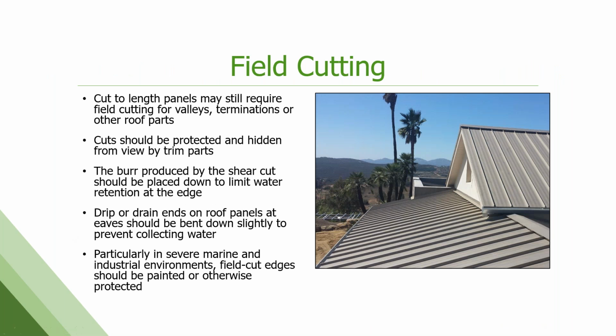Field cutting. Yes, field cuts happen. They need to happen. Valleys, terminations, etc. They should be protected and hidden with trim as much as possible, if that's possible. The burr made during the shearing and cutting action should be down, which allows water to drip off that edge and not hold onto it. And then you can even slightly bend or downturn cut ends or eaves as well to prevent water pooling and capillary action holding on that cut edge. In severe marine industrial environments, we do recommend that field cuts, if they're going to be exposed, be painted with a field paint or some kind of sealant to give them a little bit extra protection.